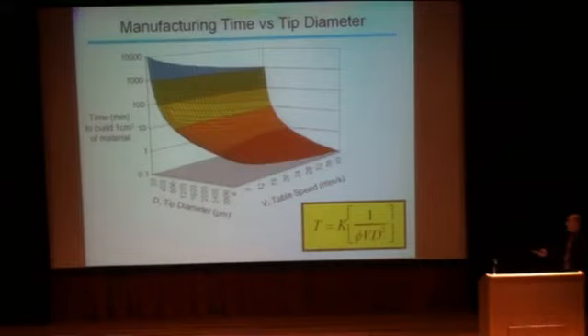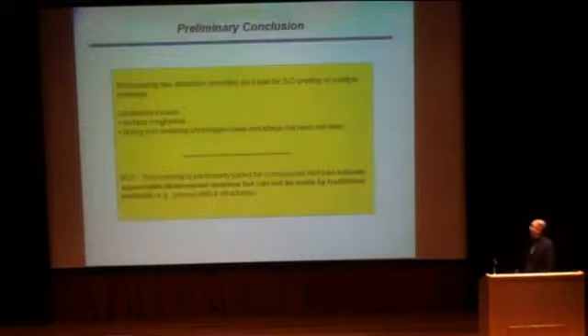And if you look at the building capabilities for Robocasting, it's related to the table speed, how fast you're depositing, but it's also inversely related to the square of the diameter. So the smaller tip size you go, the build time goes exponentially up, and now it takes you out of the range of being economical. So it turns out that where we can fit and still have adequate build times is on the order of about 400 microns and up. So that limits some of your utility.